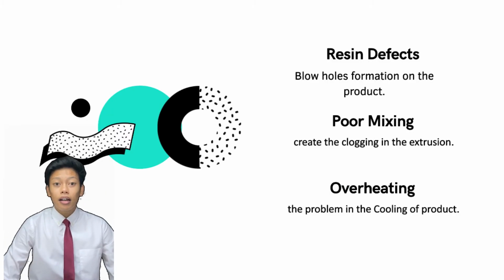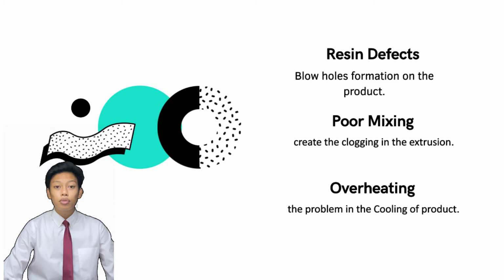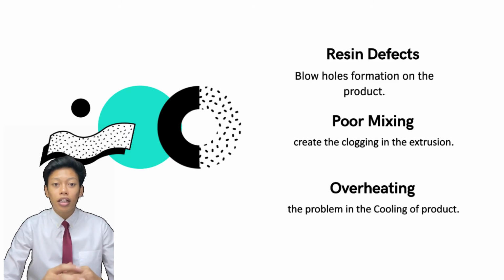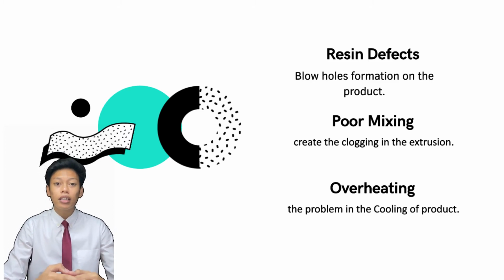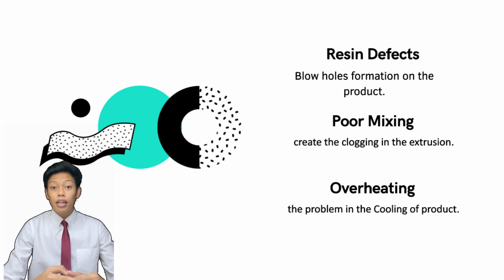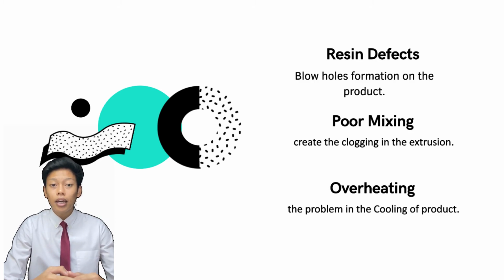Resin defects are a type of defect that can occur during the extrusion process, due to resin contamination or a chemical reaction in the extruder that may generate gases. If moisture in the resin is not removed by an atmospheric or vacuum vent, it exits the die as steam and causes holes in the product. It can also cause surface splay on the extruded part.